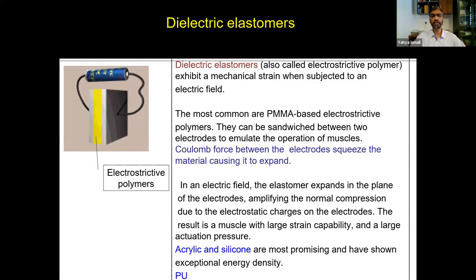The examples of dielectric elastomers are mainly acrylic and silicones, and polymethyl methacrylate (PMMA) based electrostrictive polymers. By applying a voltage of around 50 to 100 volts, they start creating movement. In the electric field, these elastomers expand in the plane of the electrode, amplifying the normal compression due to the electrostatic charges in the electrode. This is the mechanism in dielectric elastomers.